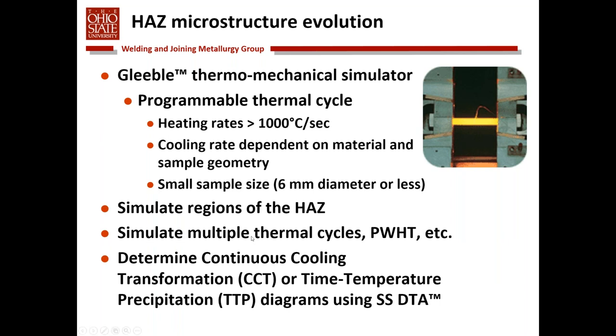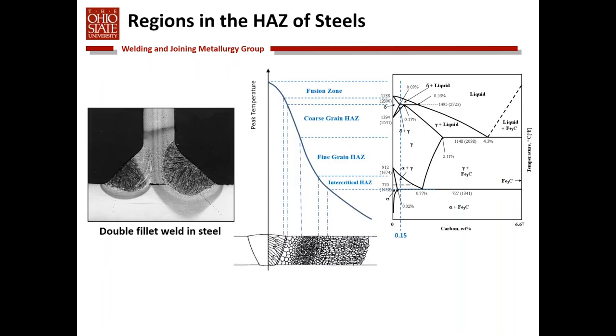It can also be used to simulate multiple thermal cycles, post-weld heat treatment effects, etc. So any thermal cycle that a heat affected zone sees, typically you can simulate using the Gleeble. It's also been widely used to develop continuous cooling transformation diagrams or time temperature precipitation diagrams. We use, again, this single sensor differential thermal analysis technique to basically measure those transformation temperatures.